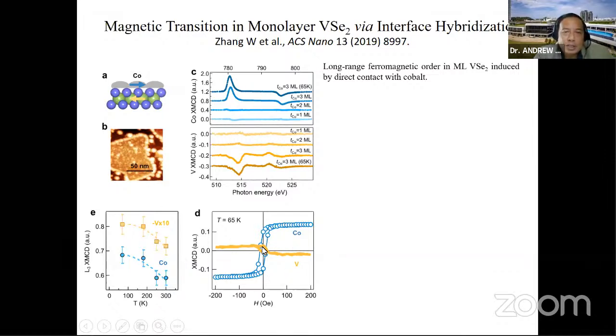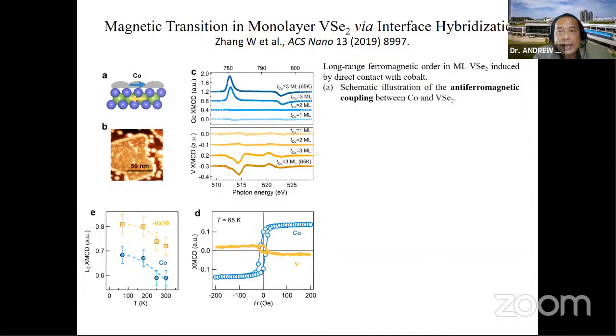And here you can see the data, the indication of ferromagnetism. And we noticed that it's antiferromagnetically coupled between cobalt and vanadium diselenide. That's why these hysteresis curves are opposite way around. So the cobalt is this way and the vanadium is the other way, right? And we can see the hysteresis in this case.